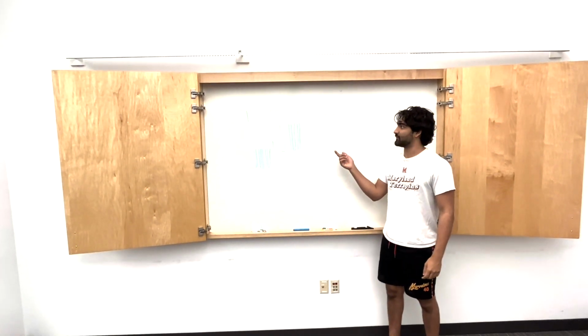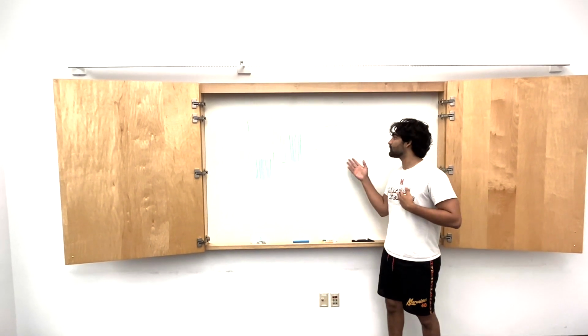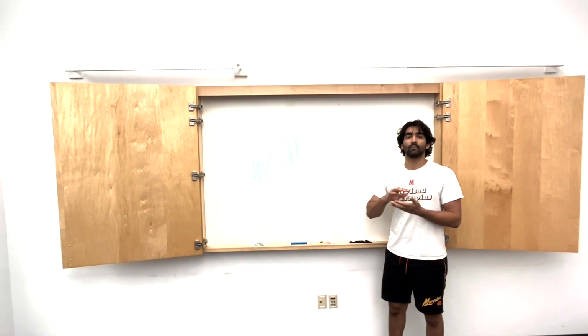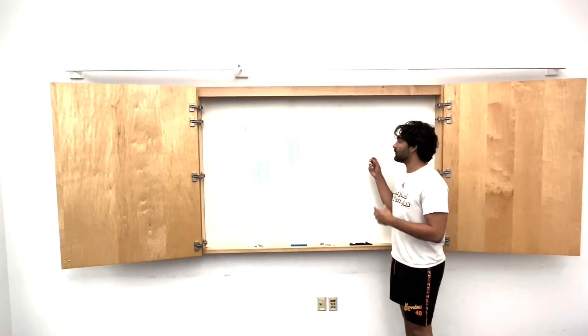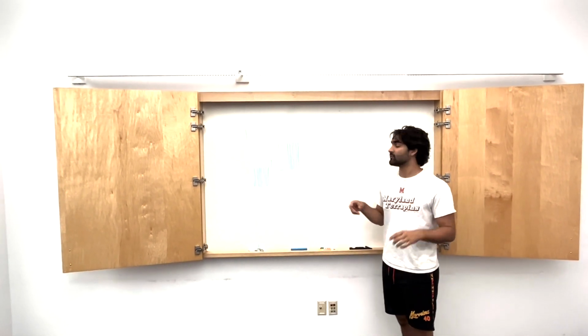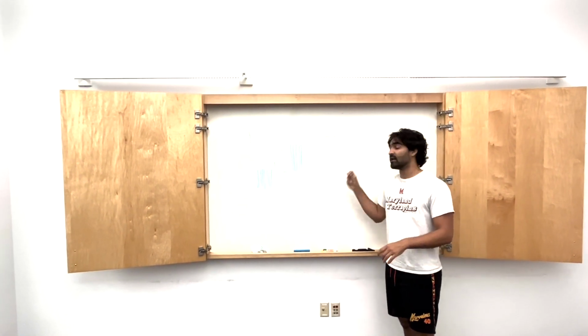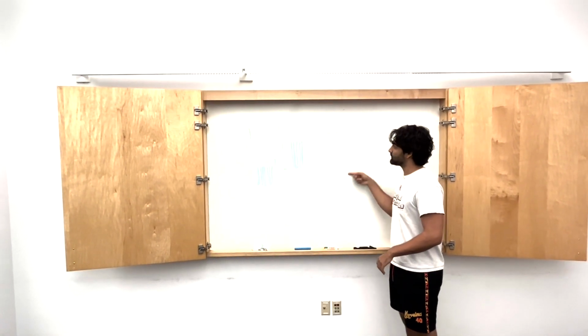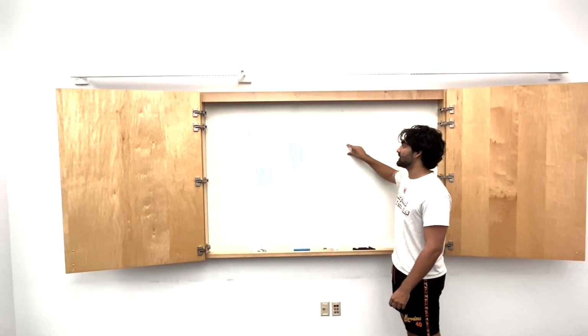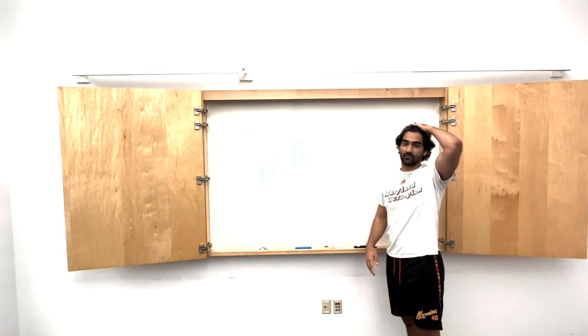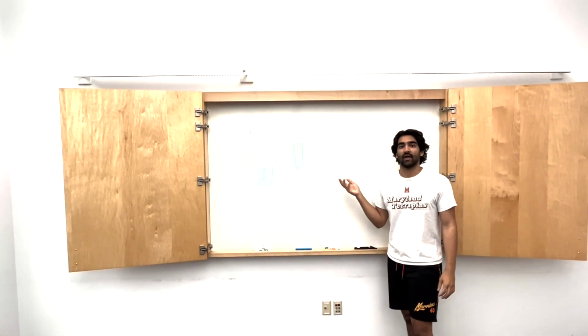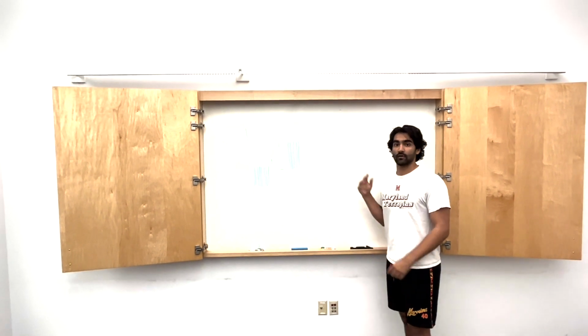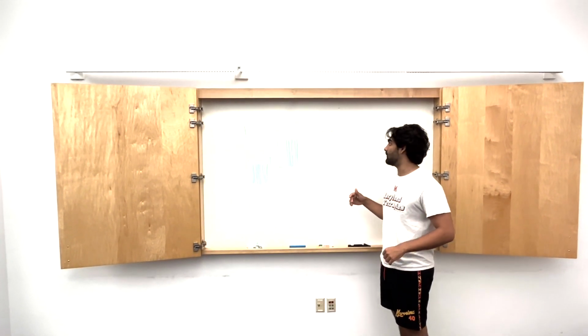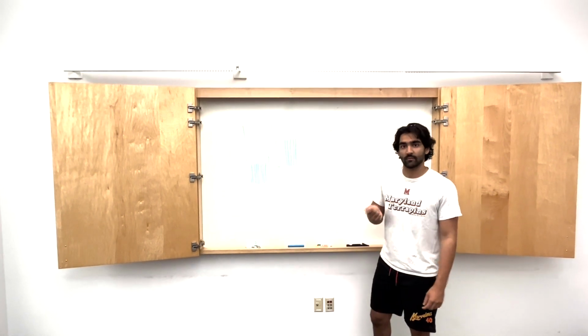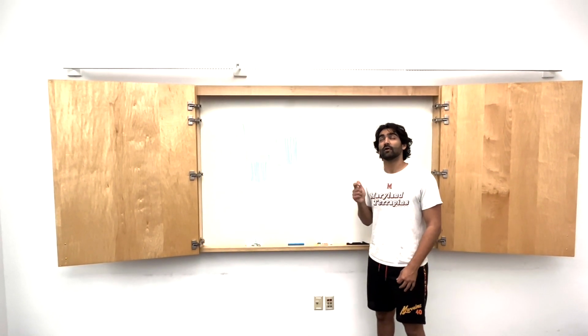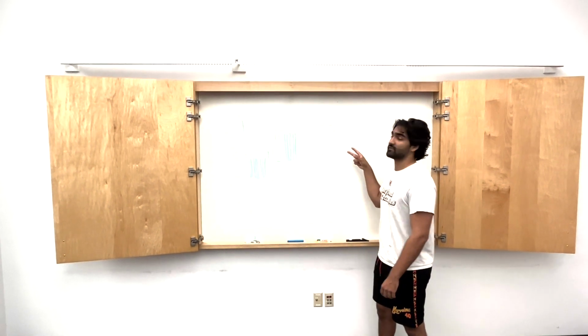As for the processing of our material, we decided to use a heat press to get even sheets so that we can make our composite design. So what we did was individually use our recycled material to press out first HDPE sheets and then EVA sheets using a heat press similar to this, where two parallel plates are heated and then provide equal pressure to our material. EVA was at a temperature of around 120 degrees Celsius with a low pressure under 1,000 psi, whereas HDPE had to be cranked up a little higher to 130 degrees Celsius with around 10,000 psi.